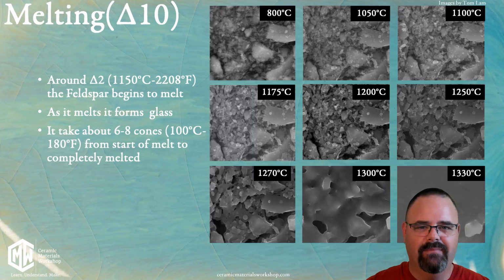And this is a beautiful transition. It is in Celsius. I'm sorry, Celsius is the language of the sciences, but you can figure it out in Fahrenheit. But at 800 degrees Celsius, we are starting, and that's pretty hot. That's already about cone almost 020. And what we can see is we've got large chunks of feldspar and quartz, and then there are lots of little clay particles. That's what all this ghosty, hazy stuff is, all of those clay particles. We go up to 1050. This is about cone